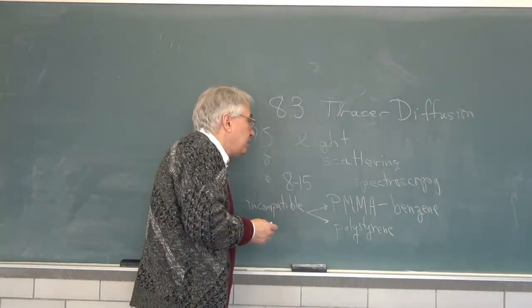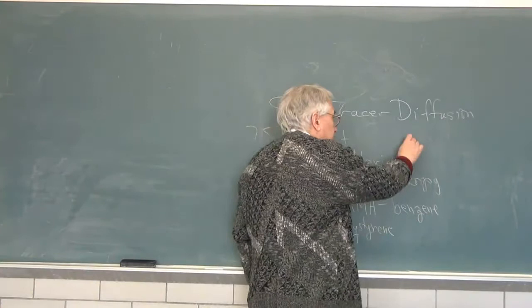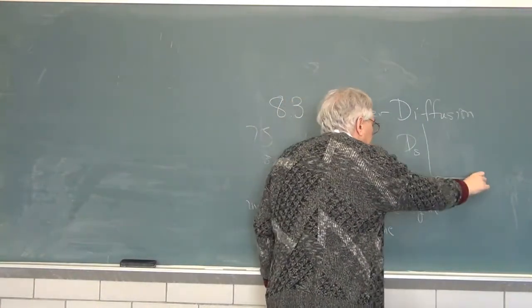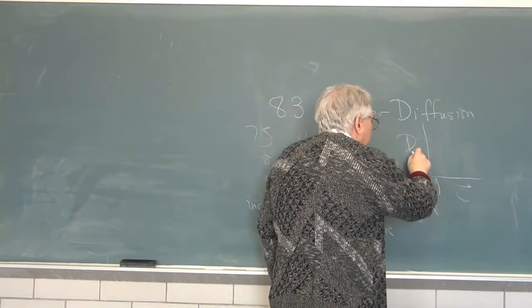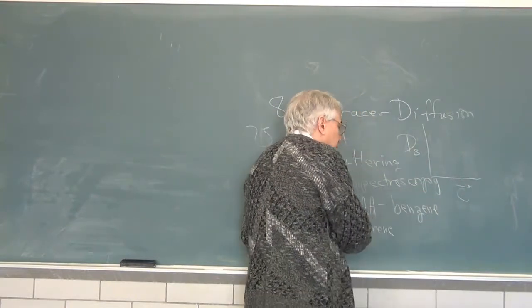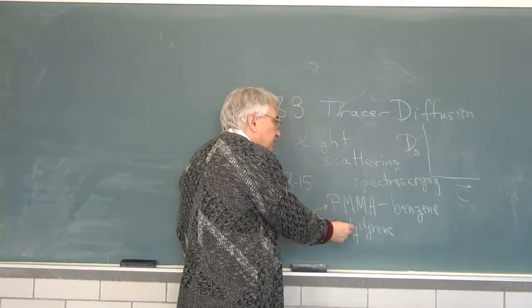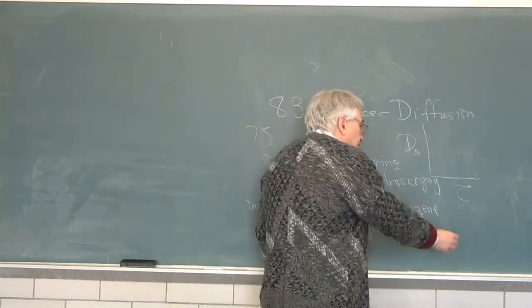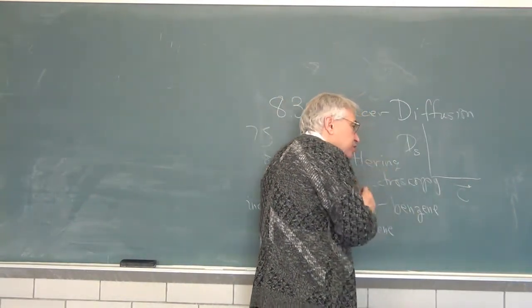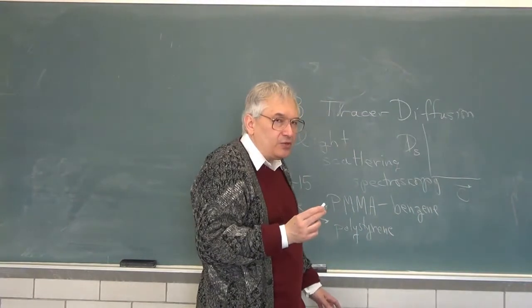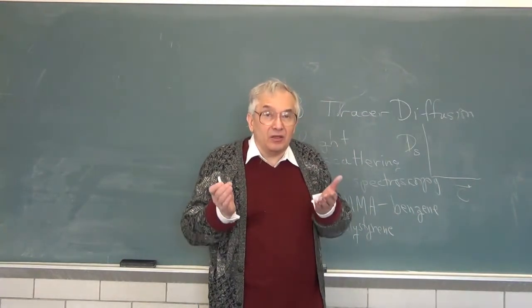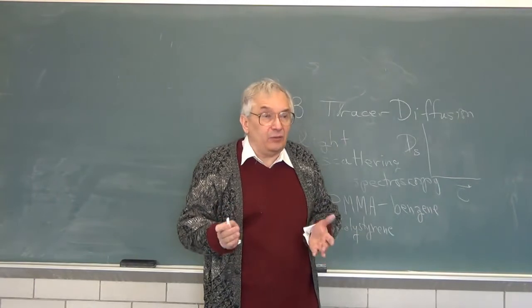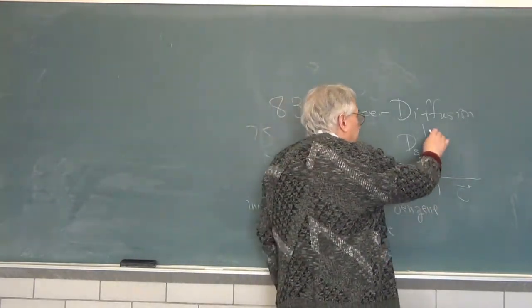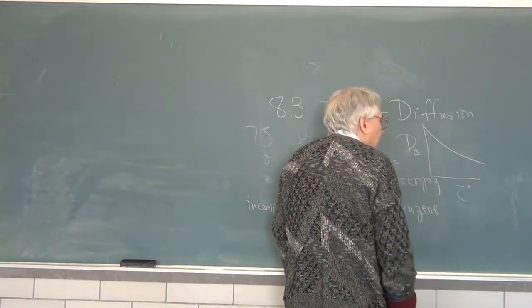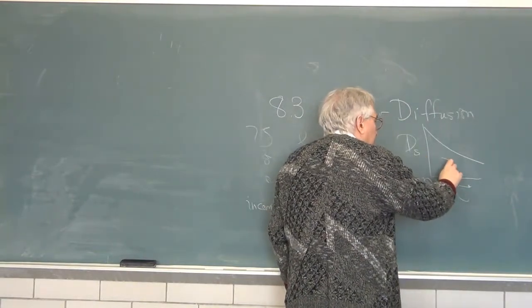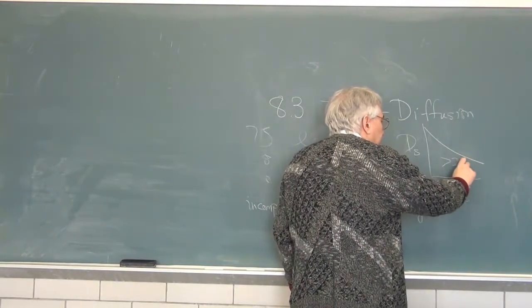If you actually look at the measurements, though, in this case, we plot the self-diffusion coefficient of the polystyrene, the species we can see, against the concentration of the matrix polymer, the polymer whose concentration we're varying, because the probe polymer is always left dilute. What we discover is there's a drop-off in D if the probe polymer is bigger than about 25 kilodaltons.